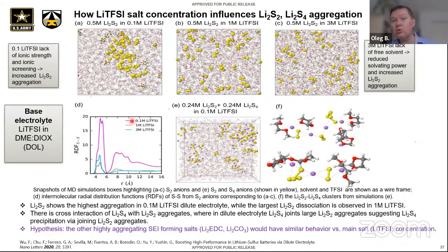So it seems the anion mediation and screening, via ionic strength-like effects, also affects the solubility of the other salts. I think that has ramifications beyond Li2S too, because we are talking about the solvent. TFSI is a strongly dissociating salt, while the other salt is very reminiscent of SEI components, which are very strongly aggregating salts.